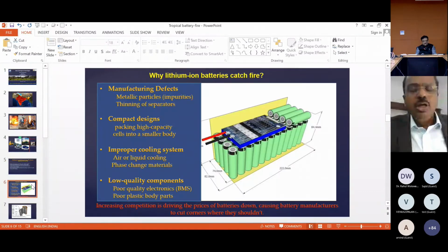Okay, so now what these guys do: in every nook and corner, there are tons of people, companies, startups that make the battery packs with half knowledge, and then they get cells which are compromised, and then they make the battery packs. So why are these on fire? Manufacturing defects, metallic particles if they don't have a clean room, and compromise in the process itself, and thinning of the separator, which will let the cathode and anode punch through during charging if you overcharge. And compact designs: you want to put more cells into the same volume, so you don't give enough ventilation space between the battery cells, and that is going to be a big problem, because your cells have to be physically separated by a distance, even with an insulator, so that the temperature doesn't move to other cells. And improper cooling system: air or liquid cooling is the best, and people are also using phase change materials.